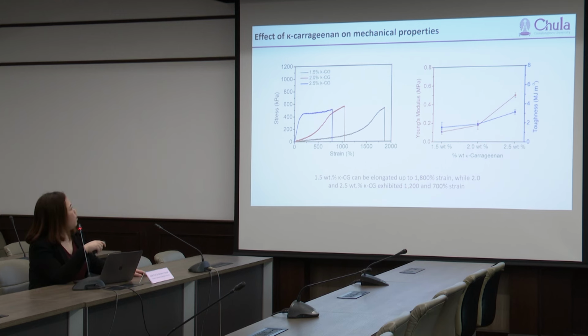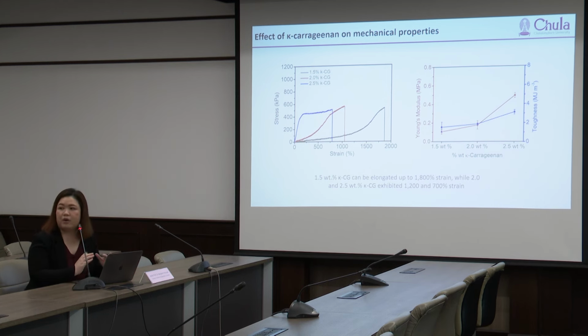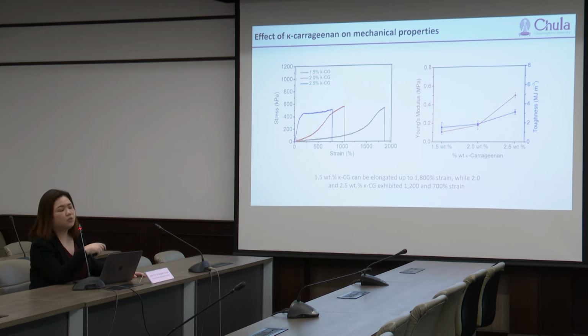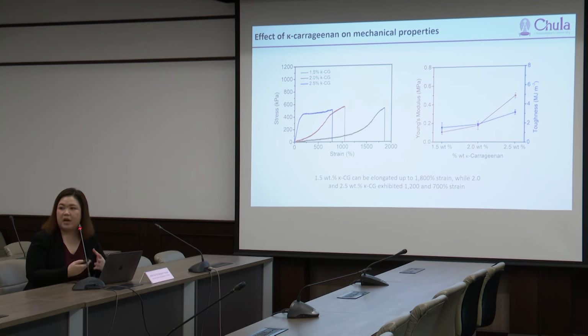So at 1.5 weight percent of kappa carrageenan, you can see that we have the highest stretchability, up to 1,800%. And then when we increase the kappa carrageenan to 2 and 2.5%, you can see that we can increase the toughness and the Young's modulus of the hydrogel. So as you can see here, we have remarkable mechanical properties of the hydrogel.